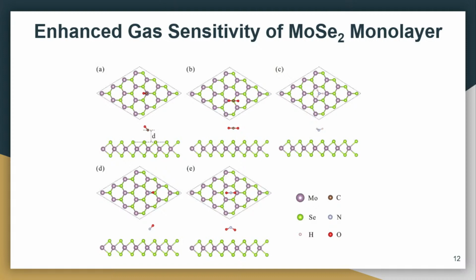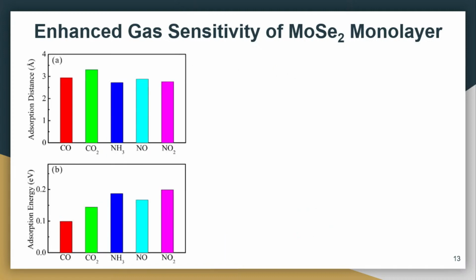What I am very much interested in is the defected MoSe2, right? But this paper is dedicated to the pristine material, but they talk about the sensitivity of this MoSe2 over these different gases, for example CO, CO2, NH3, NO, and NO2. Okay, this is the adsorption distance. They are calculating it from your substrate to your gas molecule. Here you can see that compared to CO and CO2, NH3 has a lower adsorption distance, right? And NH3 and NO2 have a similar adsorption distance compared to all other molecules. So what we are expecting is, since the adsorption distance is lower, the adsorption energy will be higher in both NH3 and NO2.